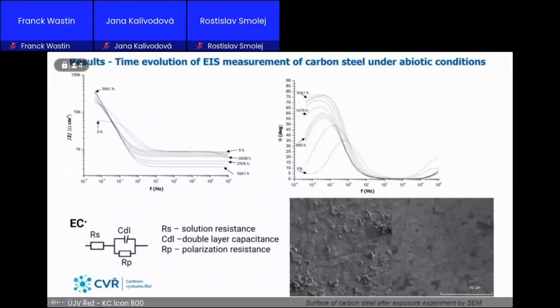And just now you can see a result from the experiment. There you can see the time evolution of electrochemical impedance measurement of carbon steel under abiotic conditions. This means without microorganisms. You can see in the figure the impedance spectra in a Bode diagram. During the whole measurement, we used only a very simple equivalent circuit.